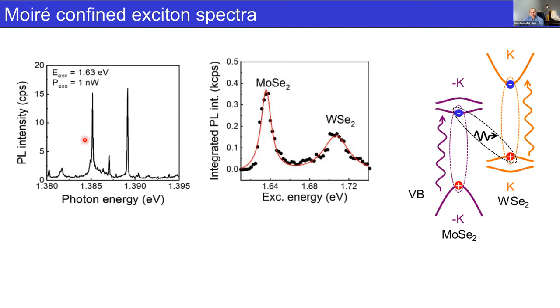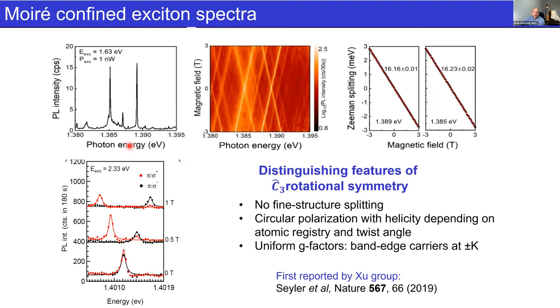This is a good indication. This is an interlayer exciton, and we see these peaks are quite sharp. So they are on the order of 100 microelectron volts, so well below the intrinsic limit of the 2D intralayer excitons in PL. And we can probe these with magneto-optics, and they have a remarkable uniformity of g factors, for instance. So as you can see in this plot here, the g factors are, I'd say, extraordinarily uniform, about 16 in this particular sample. As well, we observed that we have no fine structure splitting, which is kind of unusual for a semiconductor quantum dot-like system, because of the C3 rotational symmetry of the atomic registry of the intrinsic lattice. And then as well, we can see very clearly resolved circular polarization with a helicity depending on the atomic registry.